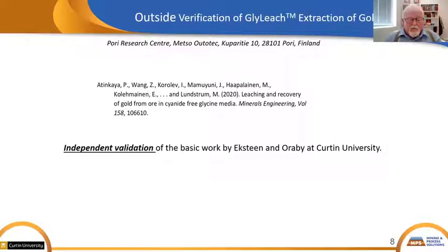What the paper concluded was that the dissolution of gold in a gold ore was partially dependent on glycine concentration, but not radically. Work by Curtin showed a very dramatic correlation between concentration and leaching rate, but that was using gold foil rather than a gold ore. The work also showed that gold extraction is highly dependent upon temperature and pH.